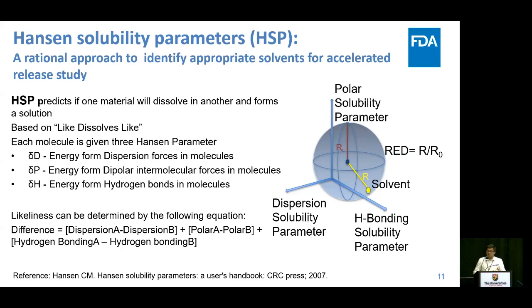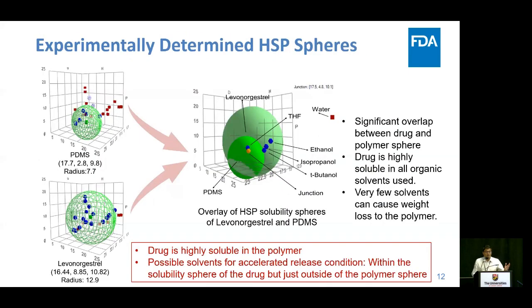So if we consider these three forces as three coordinates, we can get a solubility sphere in the 3D Hansen space. So here we experimentally determine the Hansen solubility sphere for our polymer and drug. This is the polymer sphere, and this is the drug solubility sphere. When we overlay these two, we can see that there is significant overlap of the polymer sphere within the drug sphere. This tells us a very important piece of information: the drug is highly soluble in the polymer itself. It also tells us which solvents might be good candidates for accelerated release studies.